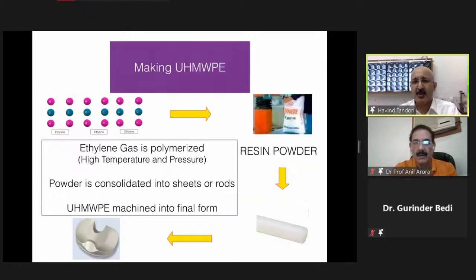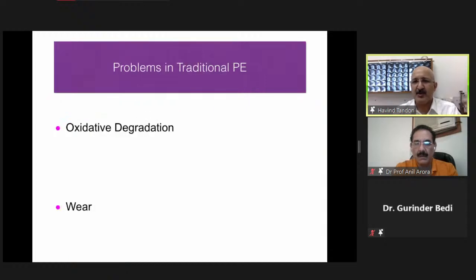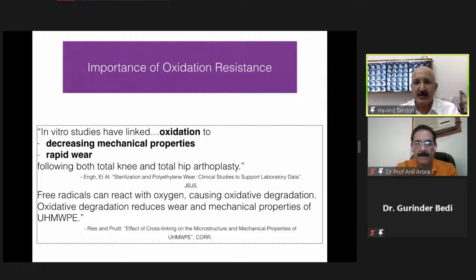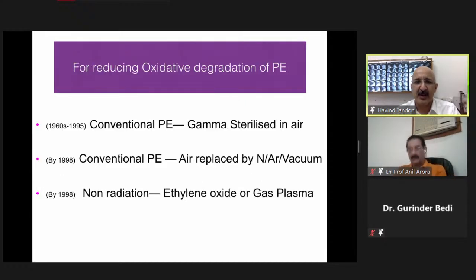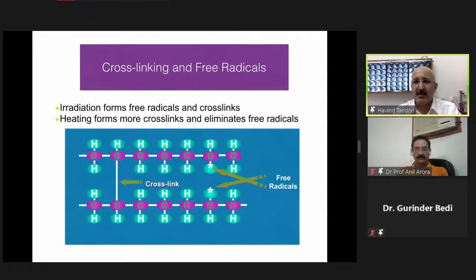This is how the process of the ultra high molecular weight polyethylene is made and then machined into the final form. The problems with the traditional polyethylene used to be, we all know, the degeneration, oxidative, and the wear, and that used to reduce the mechanical properties and increase the wear. It was found that radiation in air was being done, which was one of the main causes, and that got replaced. And then a lot of attempts were made to make the poly stronger by the process of cross-linking.